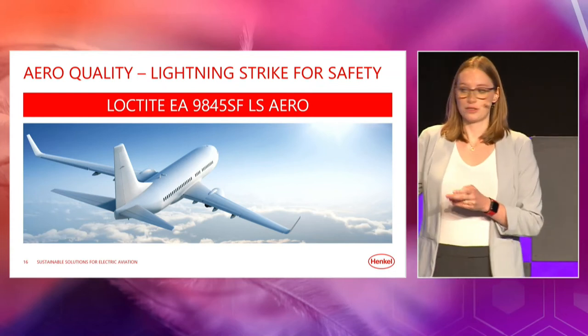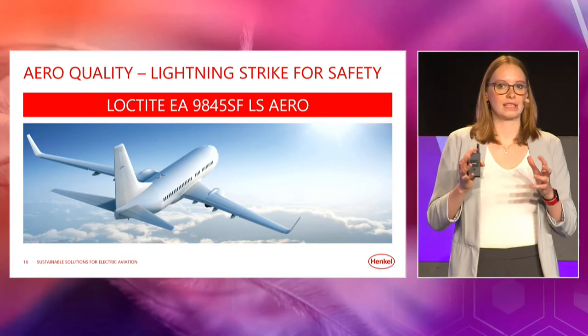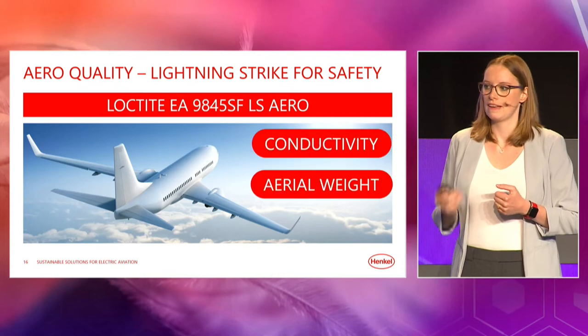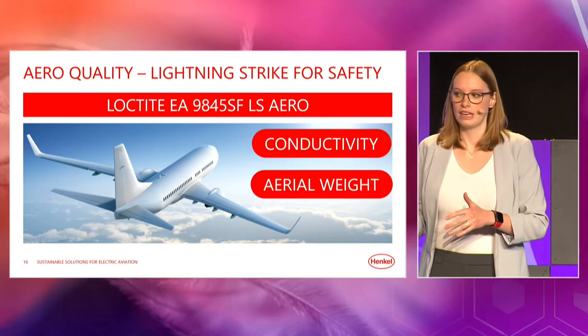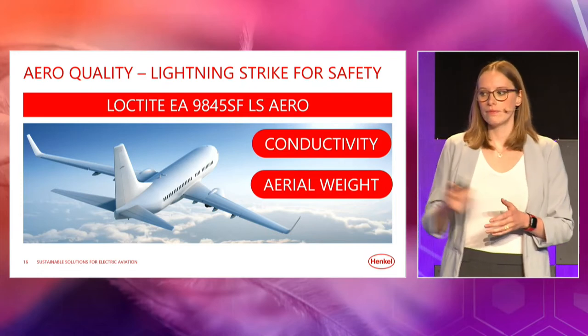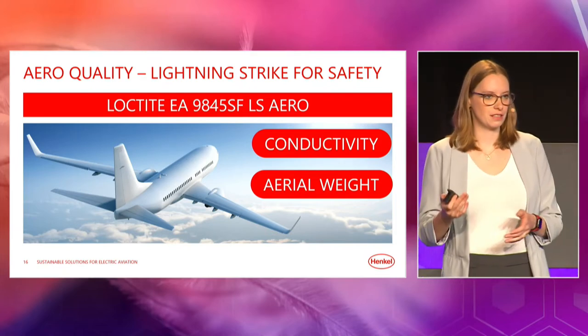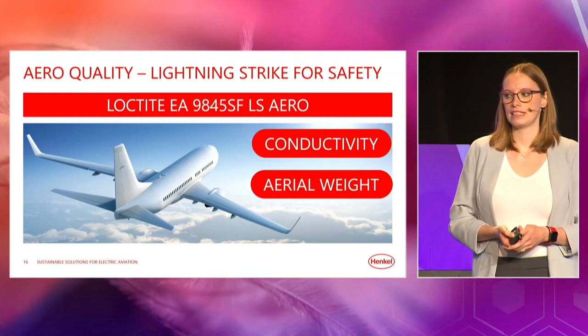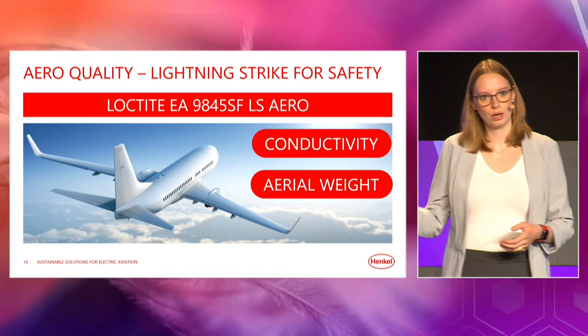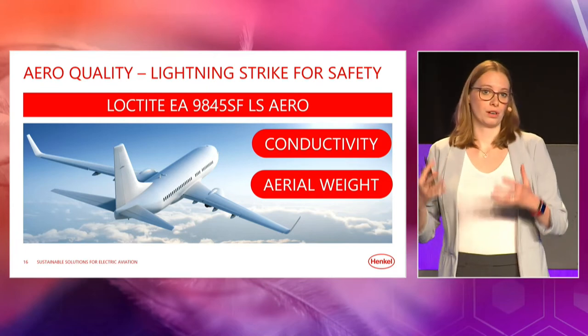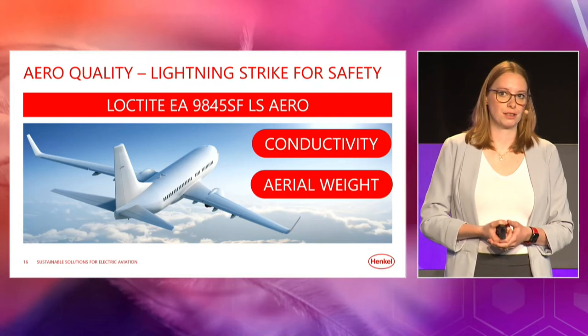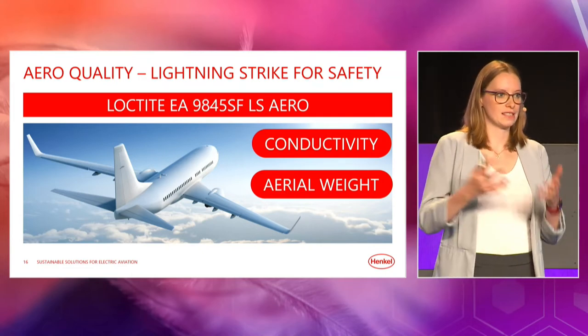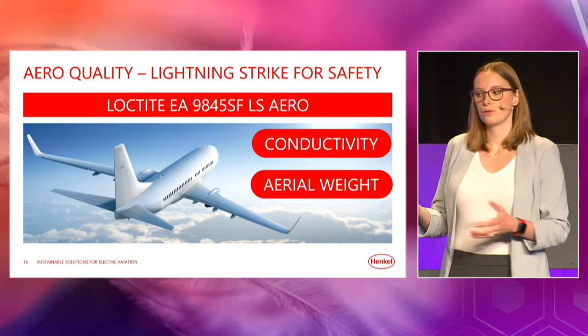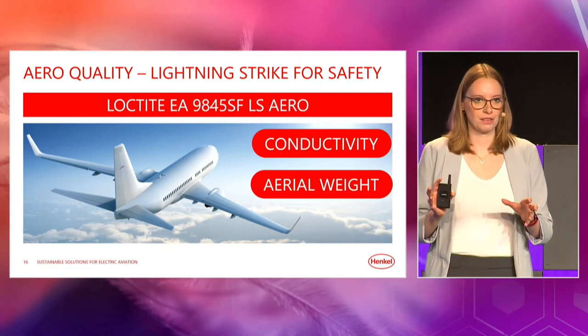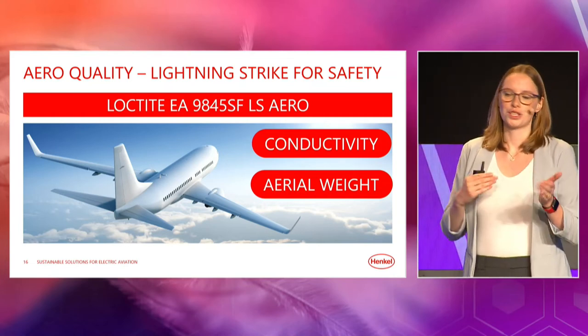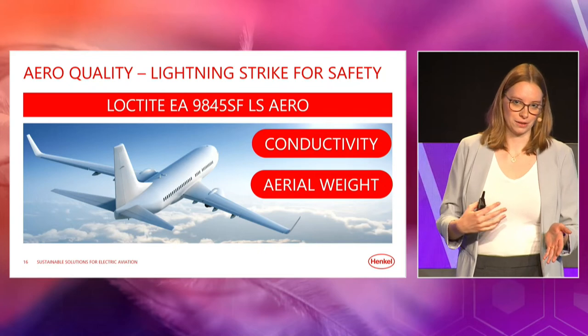And as a traditional airplane, we have different zones that need to be protected in different types. And here we have the surface conductivity versus the aerial weight. Our Loctite EA9845 surfacing film lightning strike film adhesive includes a metal mesh, copper or aluminum. And the more copper or aluminum you have inside this surfacing film, the better the surface conductivity, but of course, at the same time, the higher the aerial weight. So for the different protection zones at this aircraft, we need to consider different ratios between conductivity and the aerial weight.